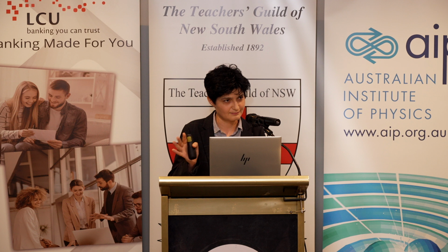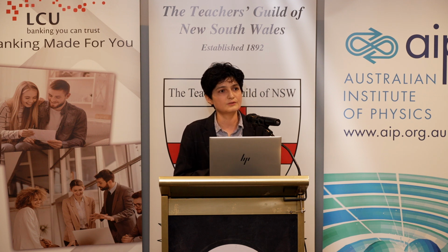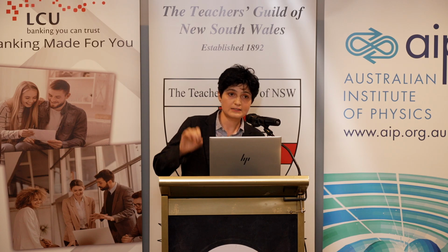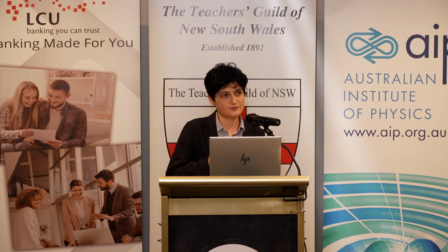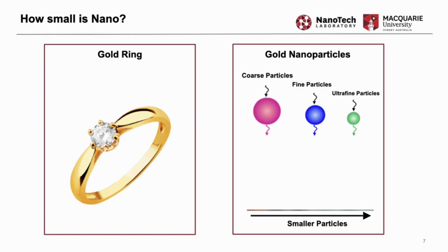Very pretty. Not that I like pink, but they are really, really pretty. They're 100% pure gold, and they're still pink. If you make them a bit smaller, from 3 nanometers to 2 nanometers, they suddenly become a bit purple. If you can, which is very difficult, make them even smaller, you might end up with gold which is blue or even green. And that is the quantum effect that we talk about.